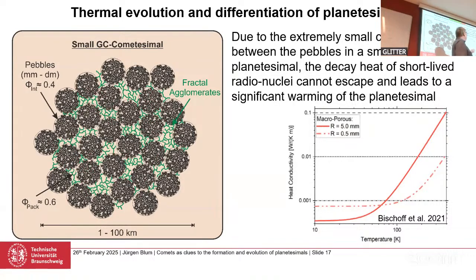This is 0. The air has the heat conductivity of here. So we're a factor of more than 10 below the heat conductivity of air, if the temperature is low. If the temperature is high, you see a steep rise, because then the radiative term, which goes as temperature to the power of 3, kicks in. And we calculated what happens if we release heat in the volume, and how the heat is transported outwards, and how an icy planetesimal would react.